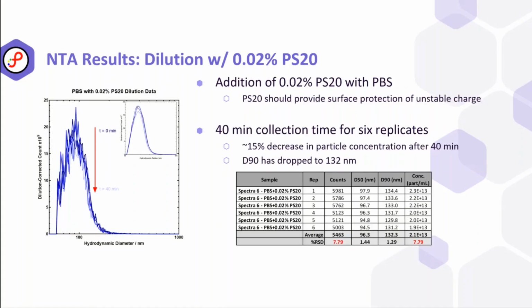So what's the next thing we do? Well, naturally, we try to throw in a little bit of surfactant. PS20 is one that's pretty commonly used in biotherapeutics. And so we added in a 0.02% PBS spiked with this PS20. And what we see is still a decrease in concentration after 40 minutes.